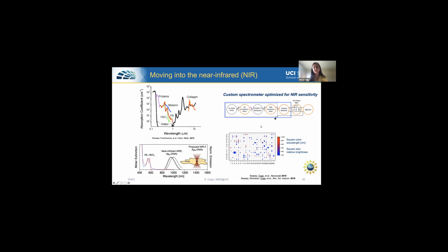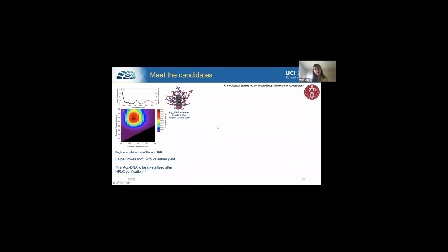So this is basically a map of different DNA-stabilized silver clusters that emit within the near infrared. You can look at this heat map here to see what the colors are of those silver clusters. By looking out in the near infrared with this new detector, we are able to find these near infrared silver clusters basically hiding in plain sight. And now we're examining them in much more detail. I'm going to show you just a few of the candidates before I wrap up.